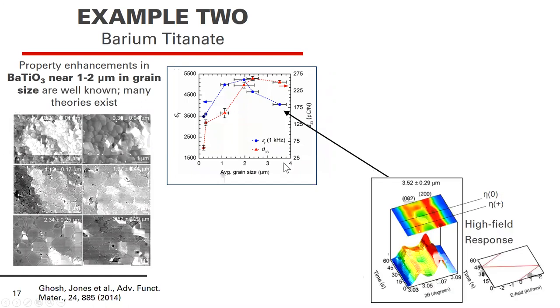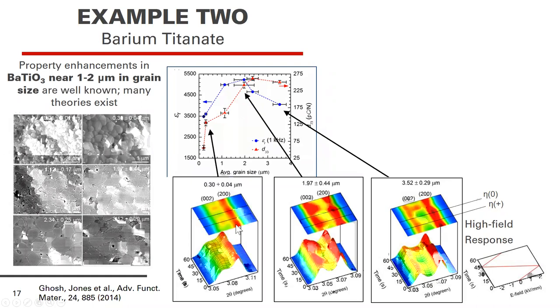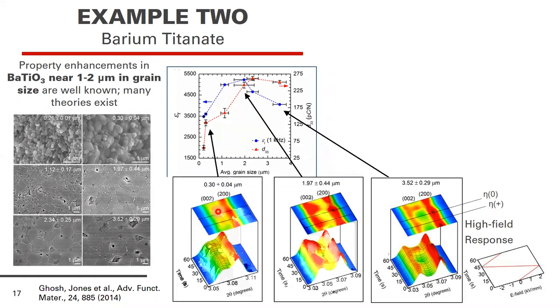And so if we take this material at a very high grain size and apply high electric fields, you can see significant amounts of intensity interchange between, say, the positive state identified here and the zero state identified here. Okay. Now, you can study this as a function of grain size. And so over here, the smaller grain size, you can see that the intensity ratio is also significant. But one of the things that you see at the intermediate grain size is that the intensity interchange is more than observed in these other two samples. So this was the high field experiment.